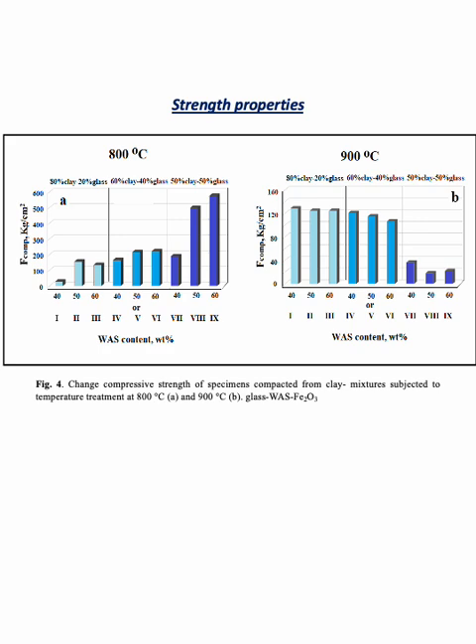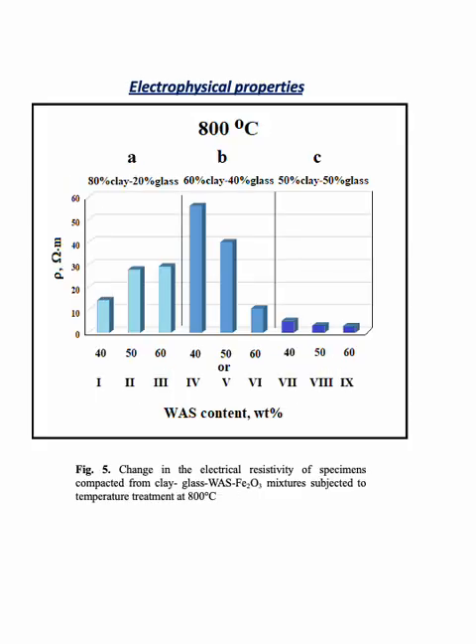We consider that this kind of ceramics is possible for application in structural wall ceramics. The measured resistance of the samples changes depending on the content of the initial mixtures, and the measurements of the samples sintered at 800 degrees Celsius showed that the samples which have a high presence of fayalite obtain values from 15 up to 55 ohm meter, and we can consider these specimens like resistors.